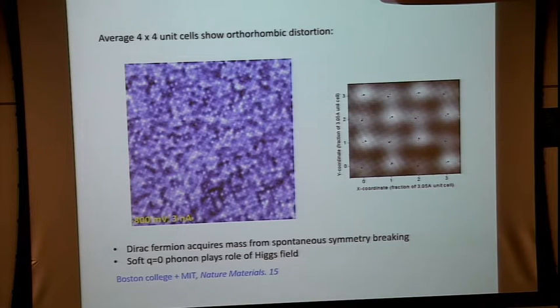There's also recent photoemission experiments from the Poland and Sweden group, and in photoemission, you see that at low temperature, the distortion onsets. Okay, it's at around 100, 200 Kelvin. Above that temperature, the Dirac fermion is massless, and below the temperature, the surface Dirac fermion acquires a mass.